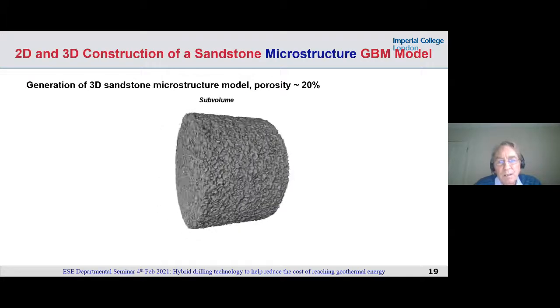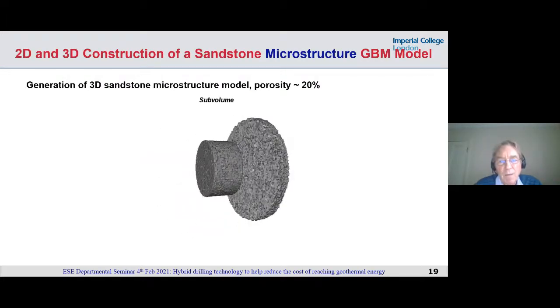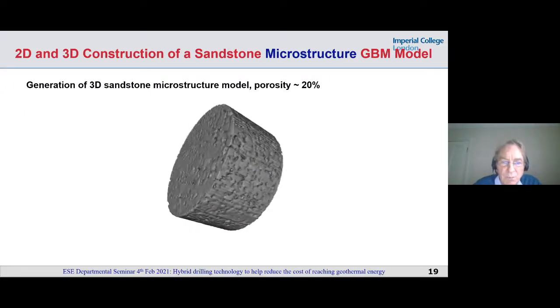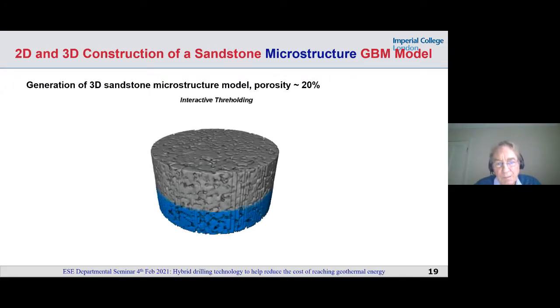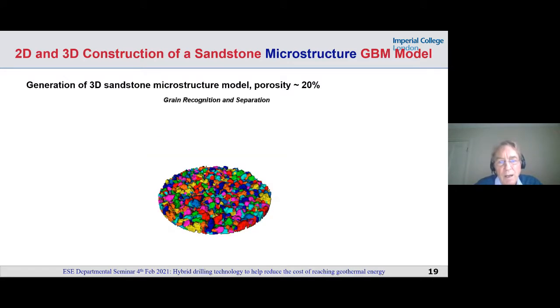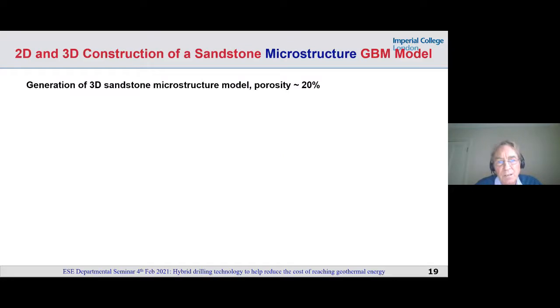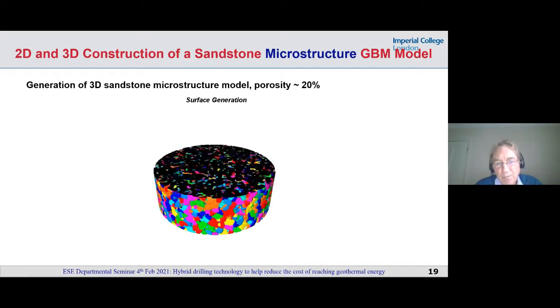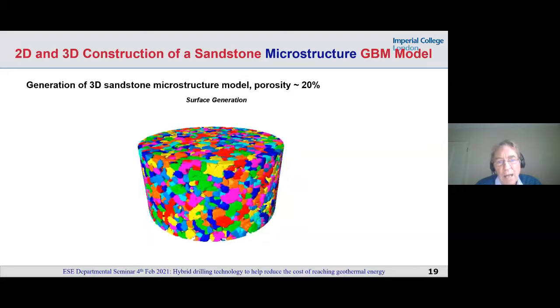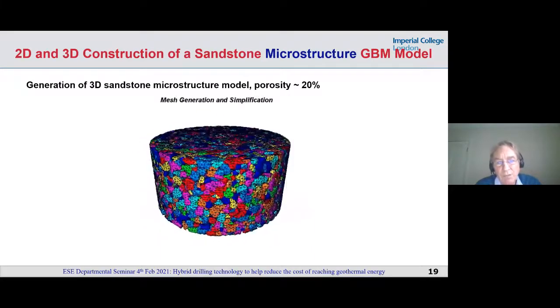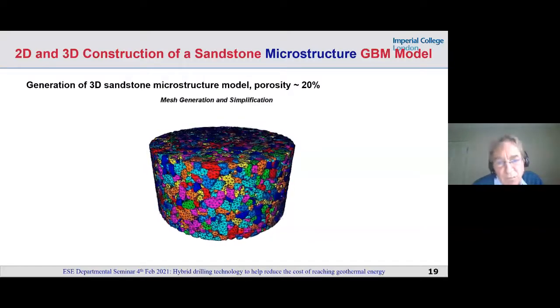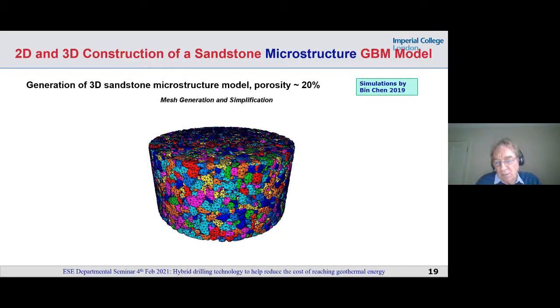We then process the data with Avizo. Now we needed a smaller sample. There was just simply too much data. This smaller sample is being thresholded using Avizo software, the grayscale thresholding. This is now finding the individual grains, and this is creating the surface meshes of every single grain. And then after we obtain these meshes, we then create the volumetric mesh for the actual individual quartz grains. Now that's quite a coarse grain. Bin Chen has developed these workflows to control the mesh resolution for the volume mesh inside those quartz grains.